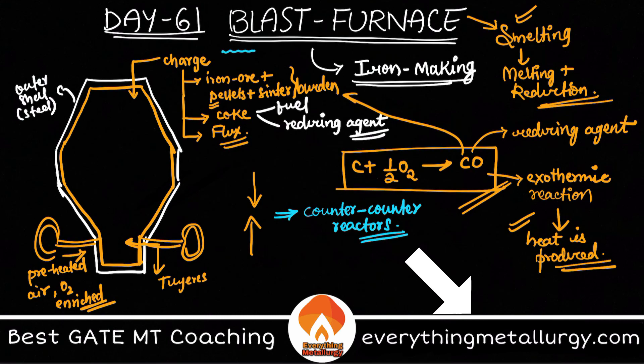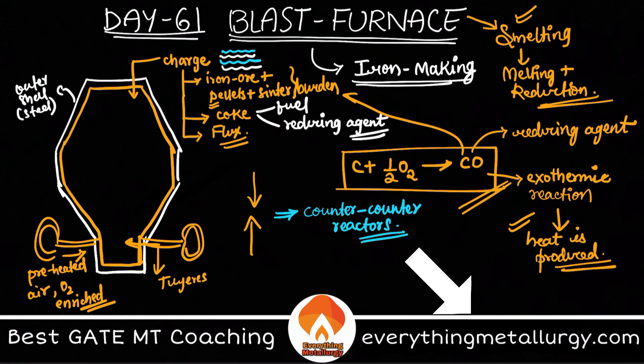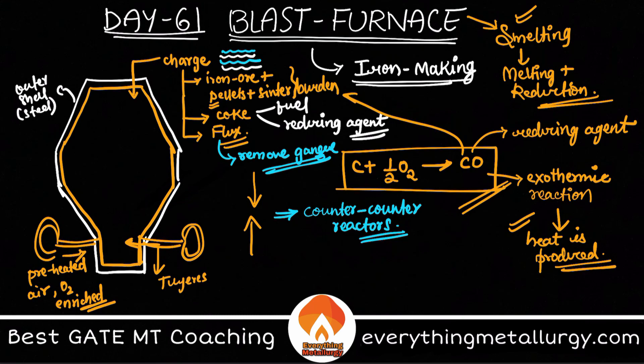The charging is done such that you see alternate layers — a layer of iron ore, then a coke layer, then iron ore, then coke — alternate layers of ore and coke. Flux can be added during sintering since sinter is produced from very fine particles. The role of flux is to remove the gangue particles — gangue is nothing but impurities — and flux like limestone and dolomite is added in the blast furnace.